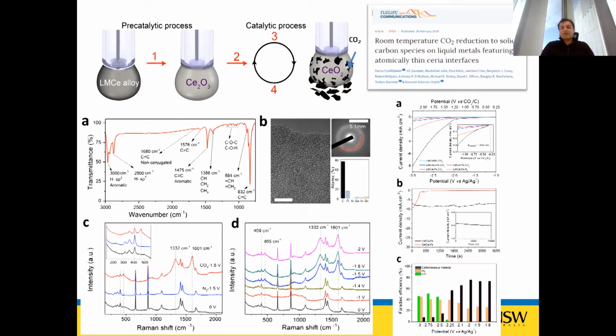Everybody is avoiding converting CO2 into anything but liquid or gas because solids remain on the surface and coat the surface. So here coking is not happening because the carbon doesn't stick to the surface and self-exfoliates. So we can, for the first time, have a system that transforms CO2 into basically carbonaceous material that we can take and burn again.